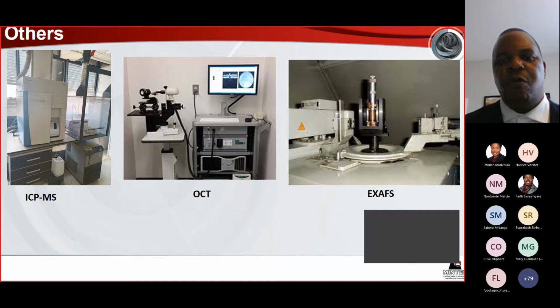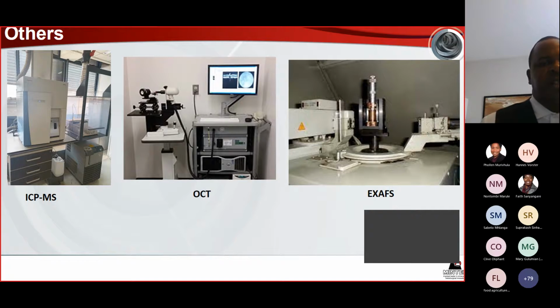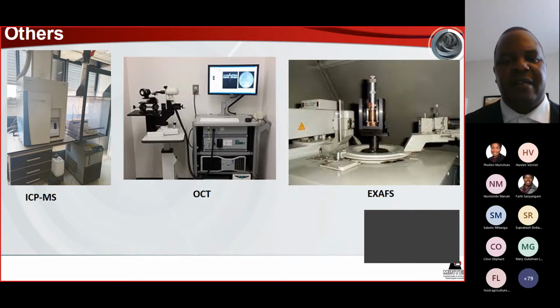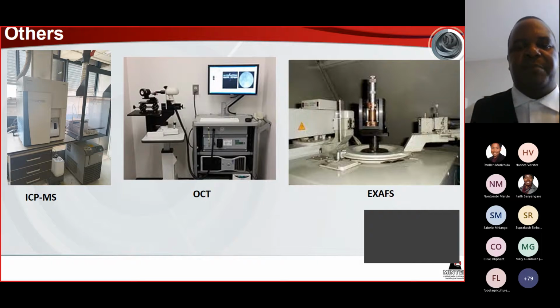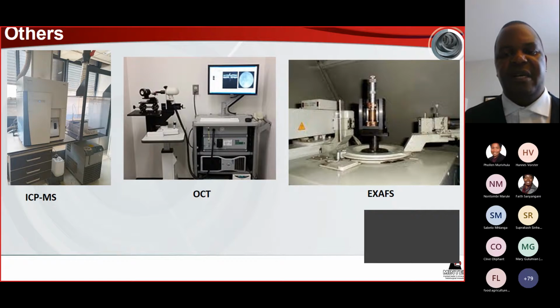However, the limitation of not always being able to measure the particle size to the greatest possible precision means that you have limitations. But we've partnered with Zululand University, and what we've done with them is to really look at mathematical approaches to determine the size as exactly as possible. Because when you start getting stacking of some of these particles, it's very difficult to determine what the real size is. And also the effects of them aggregating to form much larger particles and thereby affecting the performance of your material. So that's basically one of the areas where we use it.